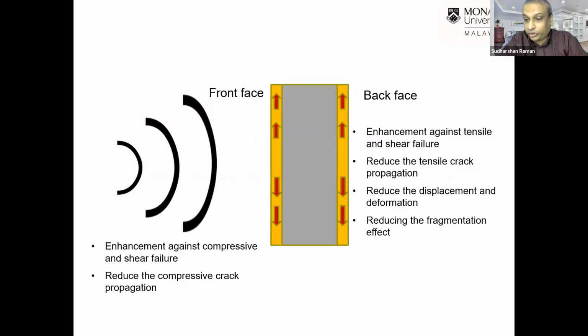But the benefits of coating on both the impact face as well as the back face or the rear face is demonstrated in this chart. When you coat it on the front face, it provides enhancement to the capacity against compressive and shear failure, and it reduces the compressive crack propagation. Whereas when you coat it on the back surface, it enhances the tensile and shear failure capacity, reduces tensile crack propagation, displacement, and deformation. And one of the major effects observed here is that it reduces the fragmentation or debris propagation, especially when they're subjected to blast and impact loading.